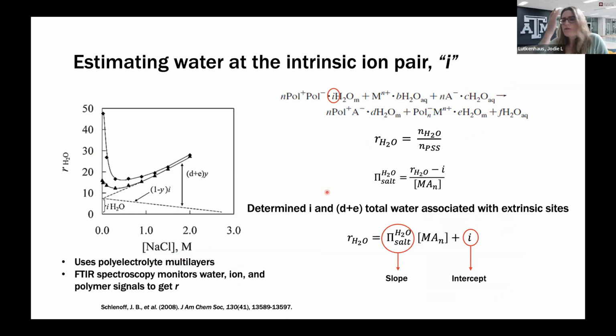So to partly explore this idea of quantifying water at the intrinsic ion pair, we turned to a really interesting paper from Joe Schlenoff's group. What he did was he used FTIR spectroscopy on polyelectrolyte multilayers, which are like complexes, but they're thin films. And he tried to separate out how much water was at the intrinsic ion pair and how much was at the extrinsic ion pair. Really the main point is that he measured this ratio of water against one of the polyelectrolytes. So it's almost like a swelling ratio.